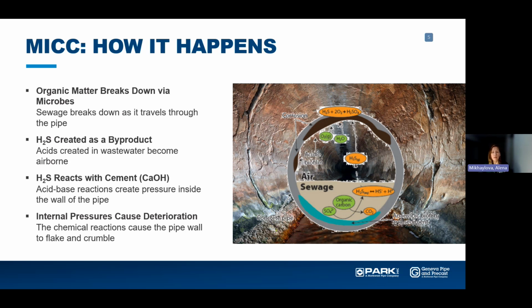So why does MIC, or microbial-induced corrosion, happen? When the sewage goes through the pipe or the manhole, organic matter breaks down and creates H2S gas. H2S gases rise to the top, and that's where you typically see deterioration of the concrete wall, as it reacts with cement and creates gypsum. Under humid conditions, gypsum starts expanding and spalling off, and that's the typical mechanism for microbial-induced corrosion. You're going to have a loss of the wall and eventually potentially corrosion of your reinforcement, which is a structural component of your structure.